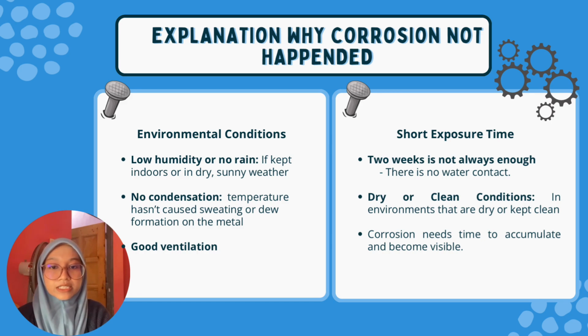We successfully evaluated the effectiveness of corrosion prevention using spray coating on steel nails. Over 14 days, we observed all four samples, coated and uncoated, which were placed indoors and outdoors. Surprisingly, none of them showed visible signs of rust. Some key points that we observe from the experiment, which is the influence of the manufacturing layer, especially surface treatment.